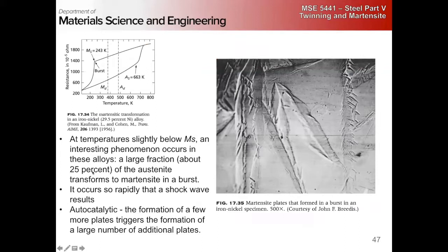And again, this is something you can hear with acoustic emission. You actually get a propagating elastic shock wave through your material that you can pick up acoustically, right? And essentially, it's an autocatalytic effect, a self-accelerating effect, like a nuclear explosion.